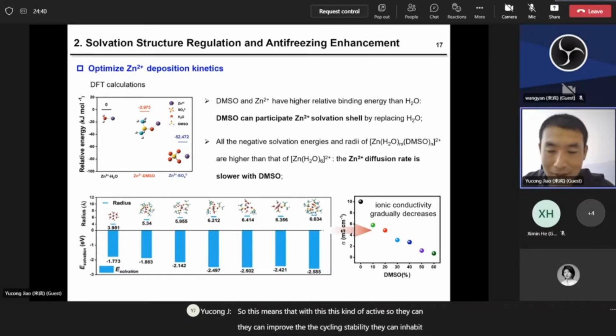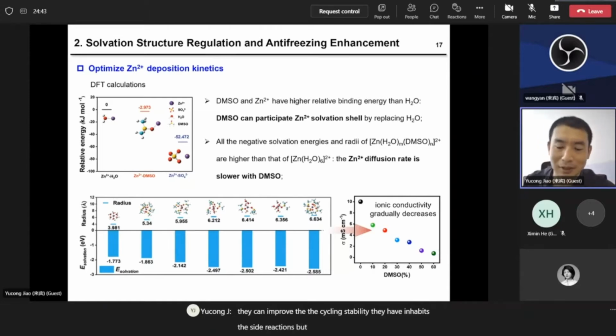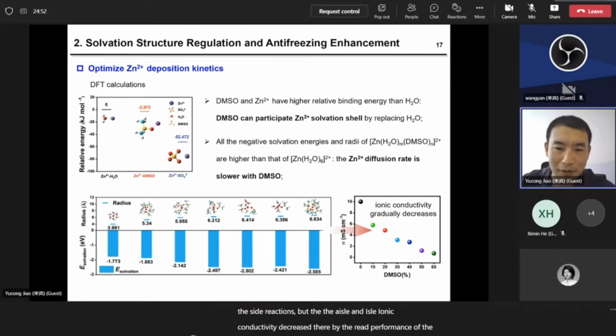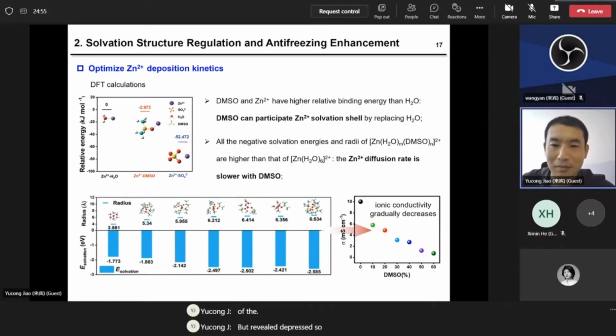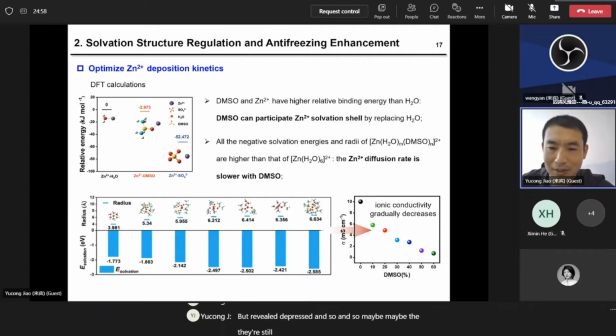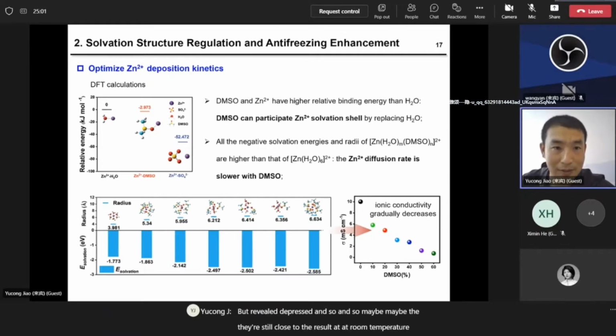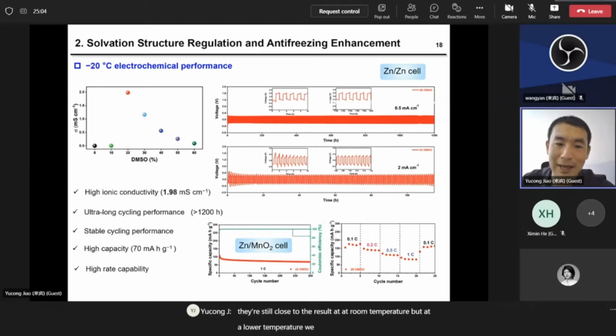They can inhibit the side reactions, but the ionic conductivity decreased, thereby the rate performance of the battery will decrease. So maybe they are still close to the result at room temperature, but at lower temperature we can see that the ionic conductivity decreased more significantly, and thereby when we assemble the zinc manganese dioxide battery, the cycling performance is much poorer than room temperature, and the capacity is much lower than room temperature.